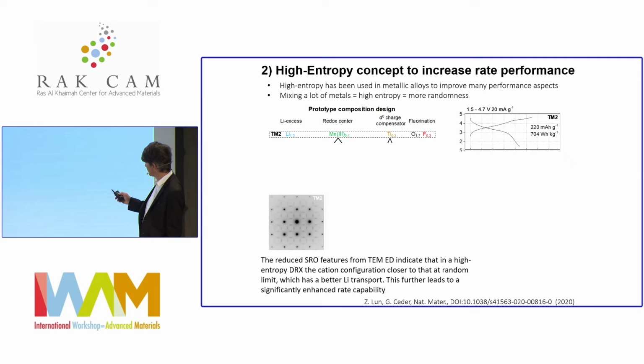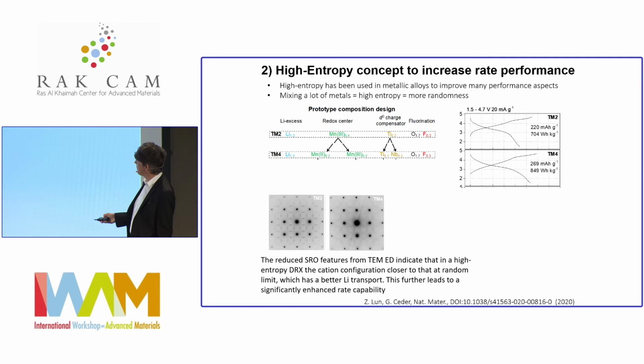and it gives you sort of respectable performance. Okay. So now I'm splitting the manganese 3 into manganese 2 and manganese 4, and I'm splitting the titanium and niobium. So from a configurational entropy perspective, I have essentially 4 metals, even though I have only 3 chemistries, but these are different valence states. You see that the short range order weakens and the performance gets better. This is all tested under the same conditions.